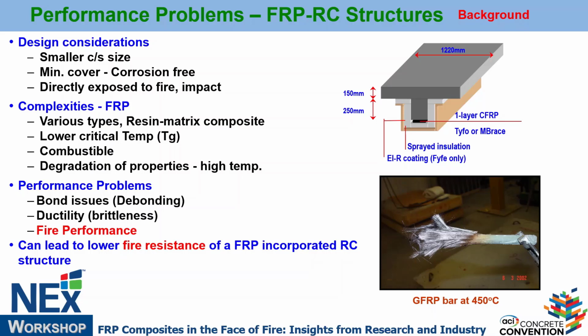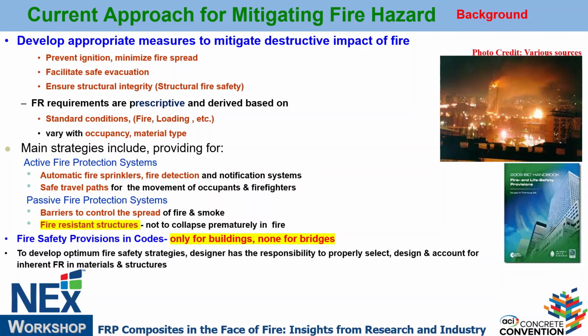Then the problem is that steel has consistent properties across almost all grades. But here, your properties change with glass, carbon, aramid. Each one has its own properties, the matrix as well as the fibers. Then you have a much lower critical temperature. Critical temperature is the temperature at which 50% of the strength is lost for steel. I will show you: GFRP and CFRP have much lower. You lose strength much faster than that. In addition, you have performance issues such as bond, even at room temperature, and ductility. So all this leads to lower fire resistance in FRP structures.